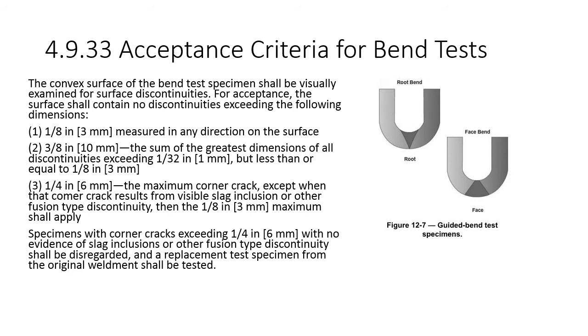4.9.3.3 Acceptance criteria for bend tests. The convex surface of the bend test specimen shall be visually examined for surface discontinuities. For acceptance, the surface shall contain no discontinuities exceeding the following dimensions. So you can't have anything, number one, 1/8 of an inch measured in any direction on the surface. 3/8 inch is the sum of the greatest dimensions of all discontinuities exceeding 1/32 of an inch, but less than or equal to 1/8 of an inch. 1/4 inch is the maximum corner crack, except when the corner crack results from visible slag inclusions or other fusion type discontinuities. Then 1/8 of an inch maximum shall apply.